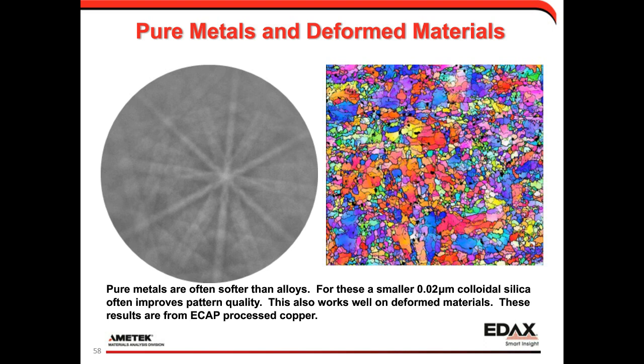And so, again, the reason I usually don't use 0.02 all the time is this consumable is just a little bit more money than the 0.05. So I use this on demand, but for pure metals or for materials that are heavily deformed. With heavily deformed, what I mean is that, on the scale of the abrasive, there's a change in lattice curvature. There's some deformation. So I want to minimize deformation caused by sectioning so that my EBSD can actually pick up the real deformation structure in the material.